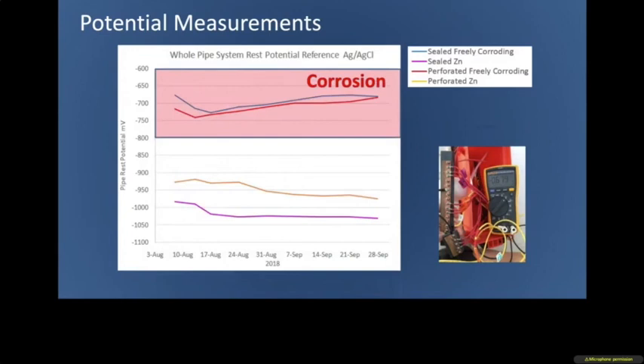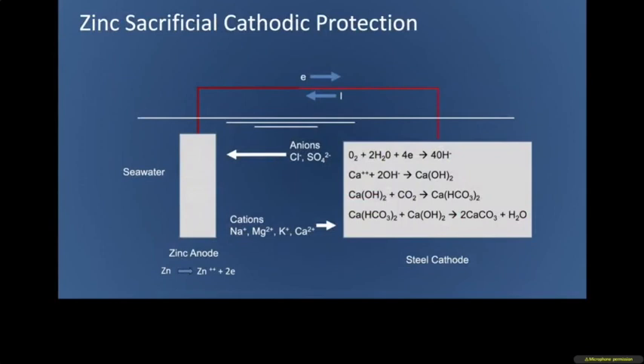If the potential is more positive than negative 800 millivolts, we're in a regime of corrosion, and that is what we saw with both the sealed and perforated freely corroding steel. And if you're more negative than negative 800 millivolts, basically you have cathodic protection and corrosion will not occur. So what that allowed us to do is to basically affirm that our systems were working from a corrosion perspective as designed. And again, we can look at the chemistry.